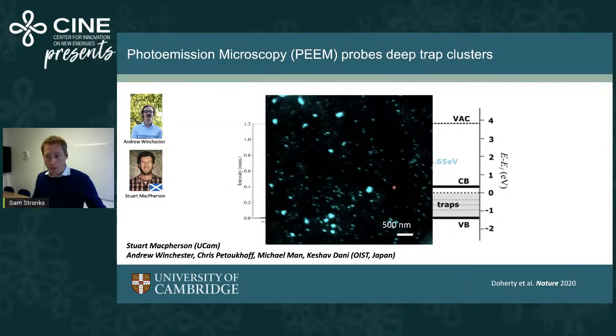And this is on a formamidinium-rich sample, which is a triple cation sample. What you see is that, quite strikingly, actually, there are clusters of these traps. So these traps tend to cluster into tens of nanometers up to hundreds of nanometer size clusters across the film. And this is a surface sensitive measurement, so these are at least sitting on the surface. And so one particularly important point is it's not full grains necessarily that these correspond to. These are smaller than the grains, which are typically at least a few hundred nanometers in size.